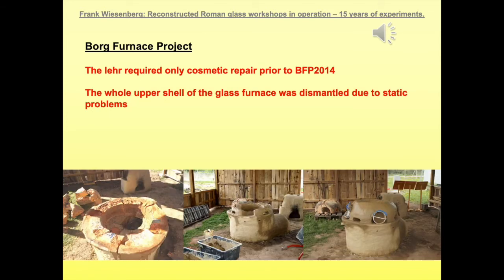The dome was taken down totally to the exterior shelf level, and a new dome with an additional small working hole, 2 large working holes, and 2 pre-warming holes was added to the furnace base. This proves that the reconstruction and a serious repair of a Roman glass furnace built from daub can be done.